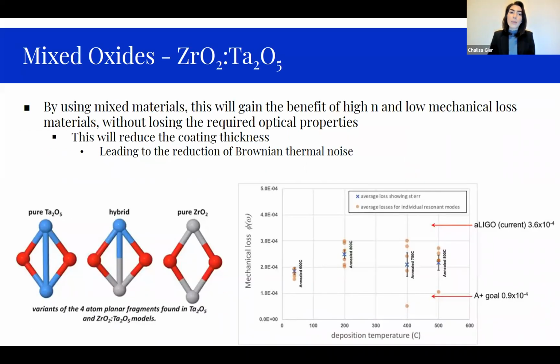Finally, I also looked at mixed oxide for gravitational wave side of things as well, which is zirconia tantala. We've chosen these two materials as both of them have high refractive index values at 1064 nanometers and 1550 nanometers. And by using mixed materials, this will gain the benefit of high refractive index and low mechanical loss materials without losing the required optical properties, which means that this will reduce the coating thickness that is needed, which then leads to the reduction of Brownian thermal noise, which is the main concern of LIGO at the moment.